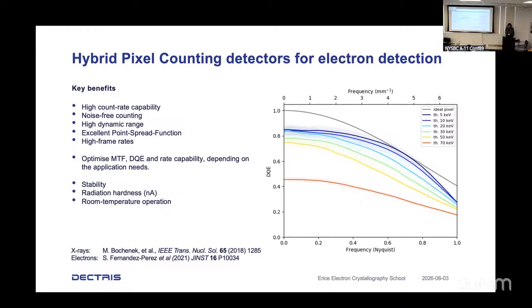So in a well-designed circuit, the time it takes to process one event is about 100 nanoseconds. So we can achieve something like 10 to the 7 electrons per pixel and second. Because of this comparator and suppression mechanisms that I explained, we have noise-free counting, and the only background is actually the cosmic background, which is of the level of 10 to the minus 4, 10 to the minus 5. So the true dynamic range is 11 orders of magnitude or higher. Yeah? It's really just depending on where your system is set up.